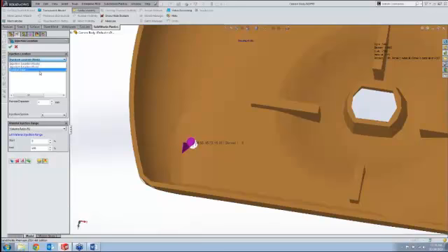Or you can do something called a control valve. And what a control valve is effectively doing is it allows you to do valve gate sequencing. So if you have multiple gates on the part that you open at different times, specifically to change the weld lines on the part, you can control the gate valves as well and when they open and close within the model. You set an overall diameter, and it will set that as well.